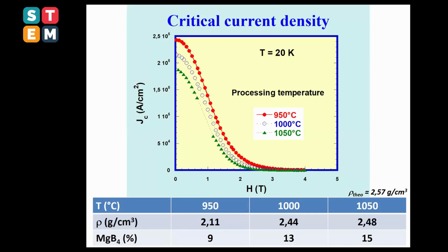The magnetic field dependence of JC clearly shows that you have different JC according to the processing temperature. But the surprise is that when you densify the material, the JC decreases at the self field when you increase the temperature. The answer is because when you increase the sintering temperature, you increase the MgB4 content inside the material. And this could be one of the reasons why the JC decreases in that case.